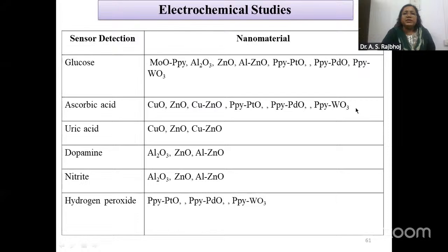Not only this, we have done our electrochemical studies. I have shown you the dopamine studies, but we have also done electrochemical studies for detection of glucose, ascorbic acid, uric acid, nitrite, and hydrogen peroxide, and we have used different metal nanomaterials. You can see the last one, where we have also used polypyrrole platinum oxide, polypyrrole palladium oxide, and polypyrrole tungsten oxide. In this hydrogen peroxide study, we found it to be very sensitive.